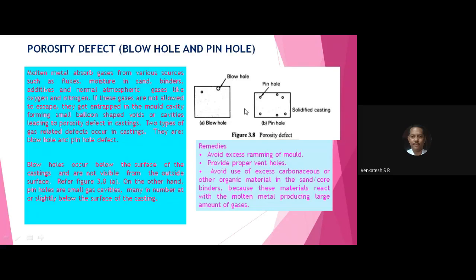This type of defect arises due to the gas or air entrapped in the liquid metal, which makes the blowhole and pinhole on the surface of the casting. This type of defect can be prevented by using the degassing method, maybe vacuum degassing or flushing of liquid metal with inert gas like argon. You can remove the blowholes and pinholes on the surface of the casting. Those are the remedies for removing blowholes and pinholes. Also, you have to provide vent holes properly in the mold and avoid excess ramming of the mold. You can then remove defects like blowholes and pinholes on the surface.